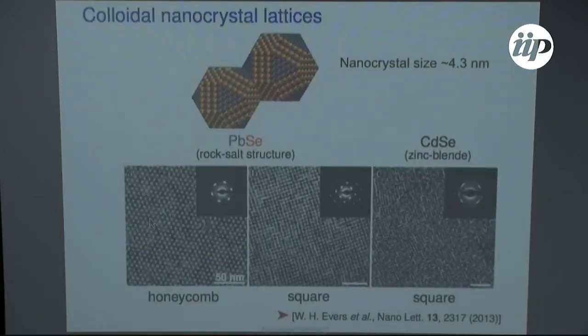Most of the time I'm showing you very old data. There is better data nowadays. He starts with lead selenide. These are the nanocrystals and they are 4.3 nanometers in size. Most of the time, they form square lattices when they self-assemble. But sometimes, and we don't know why, they form honeycombs. And you can see these are the Bragg peaks. They are quite nice. And then what they do is, after the crystal is made, they do cation substitution.